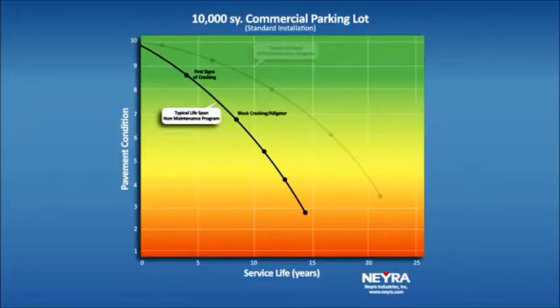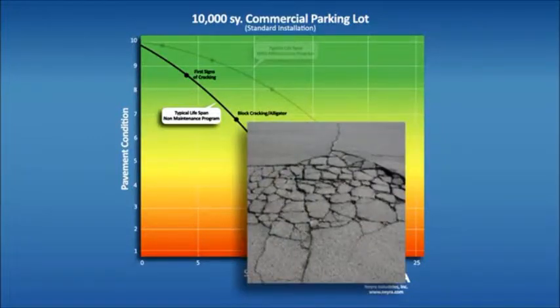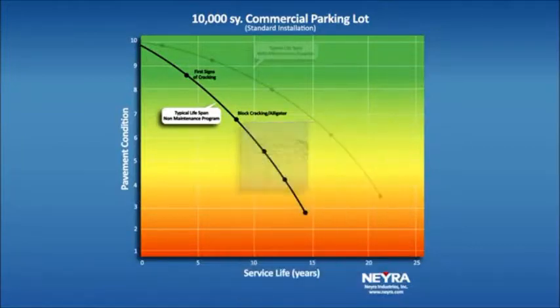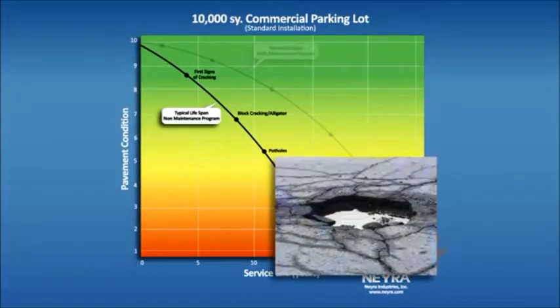As the elements continue to batter the pavement, the untreated cracks and block cracking allow water to penetrate to the subgrade, softening the base and forming cavities beneath. As vehicular traffic puts stress on these areas, the block cracks turn into alligatored areas. Around year 6 to 8, the alligatored areas, in part due to freeze-thaw cycle, are now turning into potholes. Small initially, but quickly growing with every passing year.